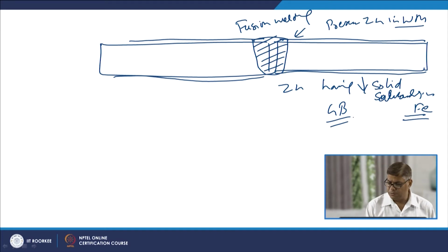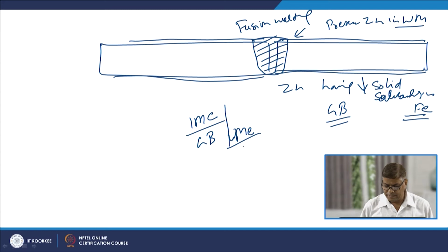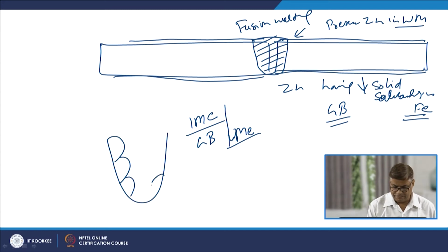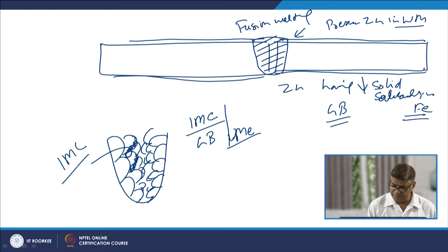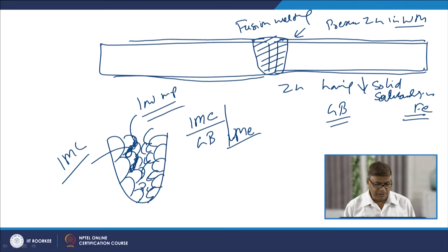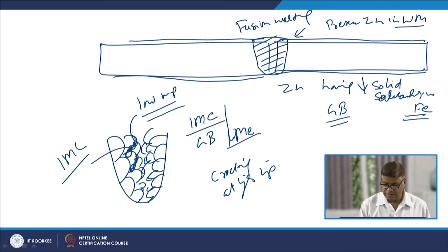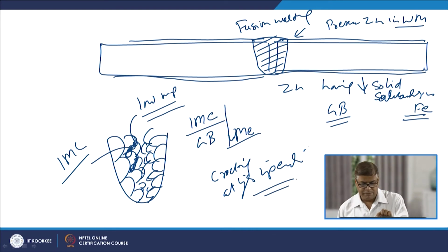So, when the zinc goes into the weld metal, it forms intermetallic compounds, as well as it gets segregated at the grain boundaries in the weld metal. Like this is the weld metal, and here we have the grains which are being developed during the solidification. So, the zinc will be present at the grain boundaries in the weld metal like this. Here it will be forming the IMC. Such compounds of zinc will have a lower melting point, which will lead to increased cracking sensitivity, cracking at high temperature.